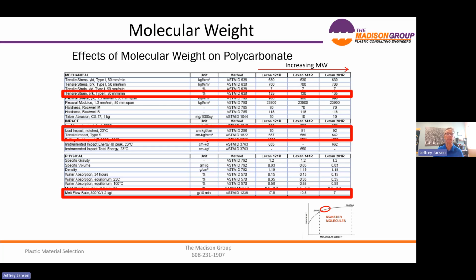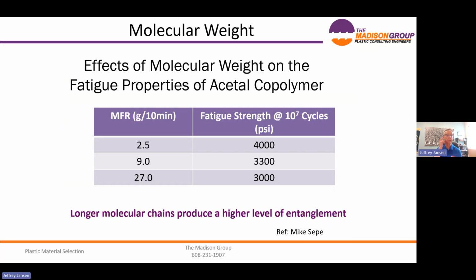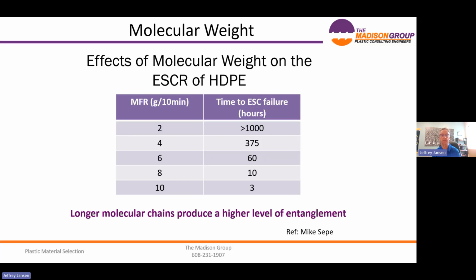Here we have polycarbonate. When we choose polycarbonate, we have a wide range of MFRs to choose from. So 7 is our high molecular weight material, 17.5 our low molecular weight material. And we see that our impact resistance and our strain at break are all better with our higher molecular weight material. Here's some polyacetal. Fatigue resistance is better with our high molecular weight resin. Environmental stress crack resistance of this high density polyethylene, again, is better when we have higher molecular weight resins.